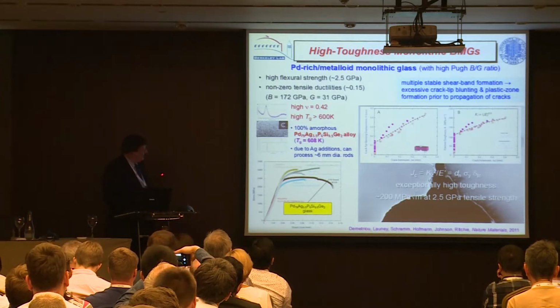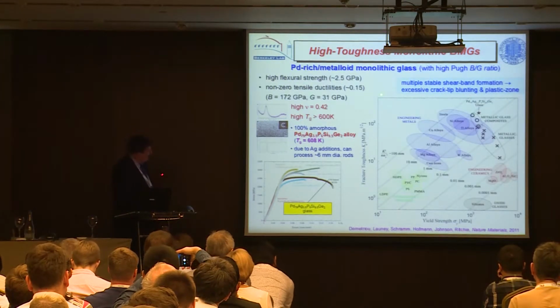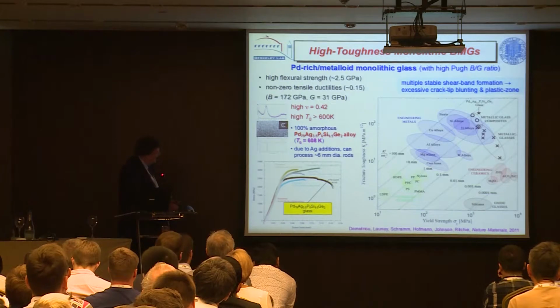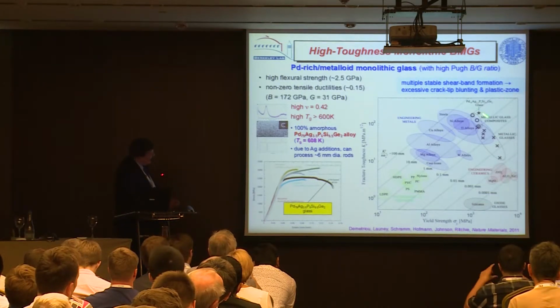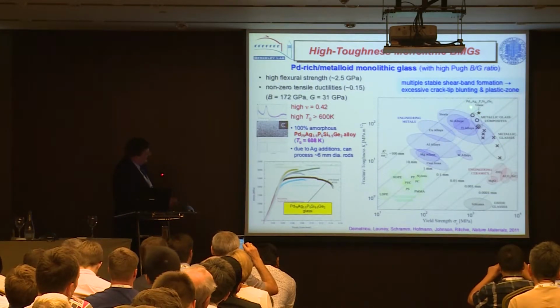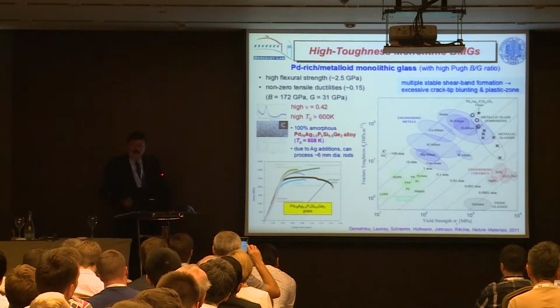These are enormous: 2.5 gigapascals and 200 MPa root meters is an enormous damage tolerance. And if you look on an Ashby plot, this is the toughness versus yield strength. We're right along here. We're right on the limit of the best there is, and this is these metallic glasses, composites, and this particular palladium glass up there. We got the front cover of Nature Materials for this.